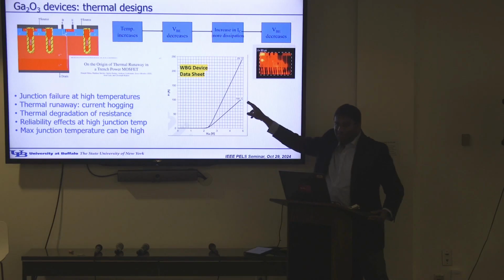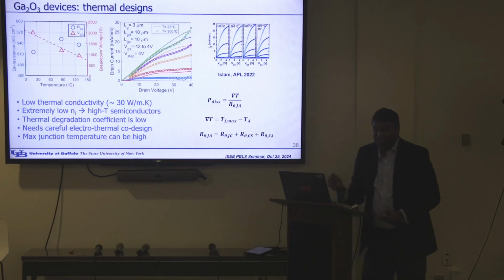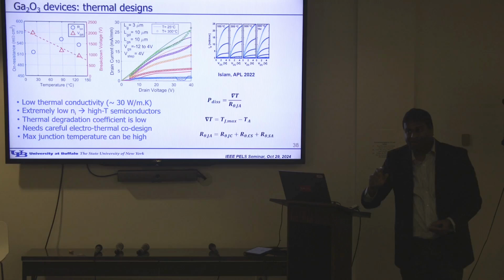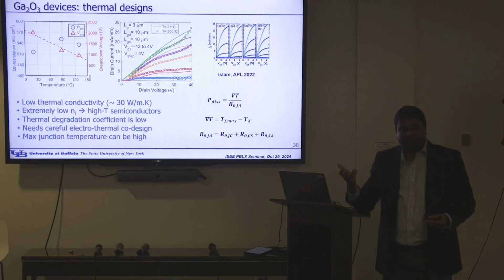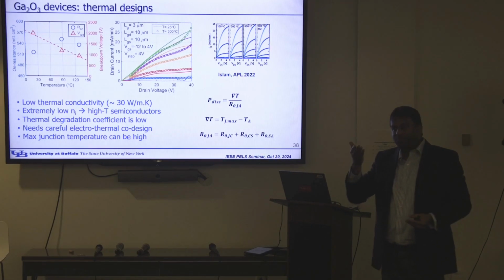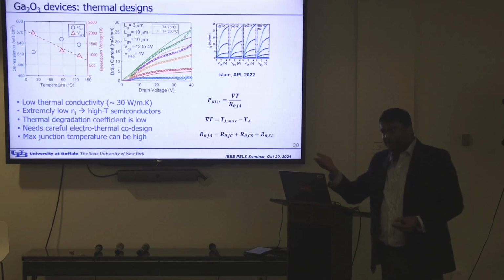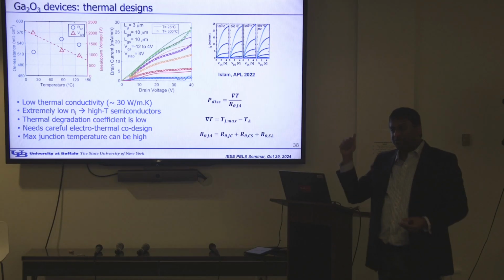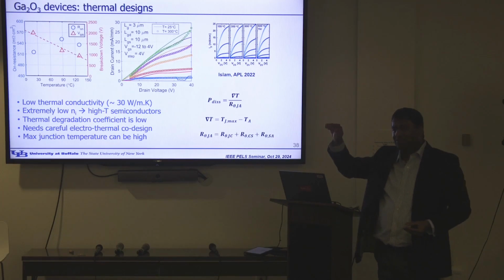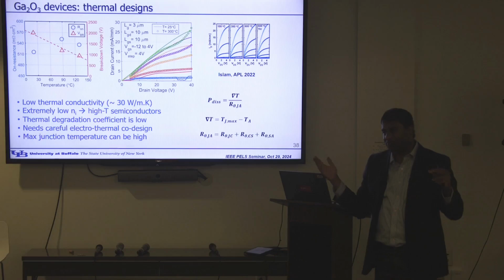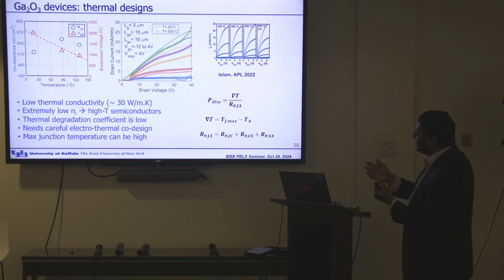drop, right? That also is unique in the sense that the mobility is already phonon limited, so it's already low, and as you go to high temperature, it's not dropping a lot, and then we get some enhancement from the contact resistance dropping. As a result, we get a slight positive, right? In a way, ideal, what we want out of a MOSFET characteristic. It just happens to be like that, right?